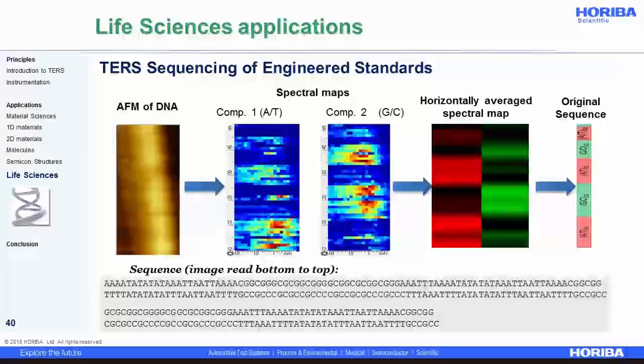You have from left to right the AFM image of the engineered DNA, the two TERS maps from the thymine and the cytosine, as we have seen just before, and the horizontally averaged map with the color intensity corresponding to those rich regions of AT on the left, the red one, and GC on the right, the green. The results are very impressive.